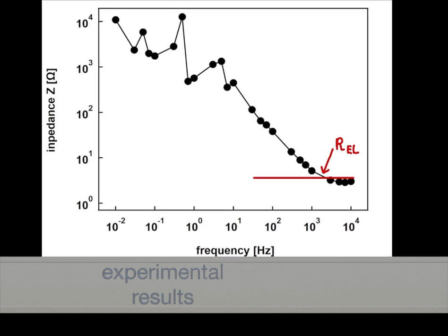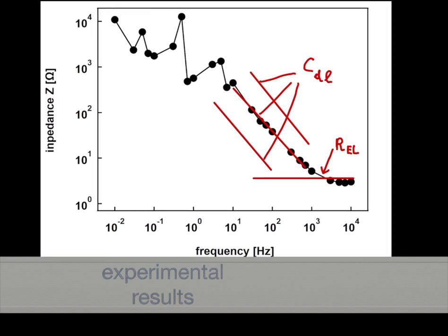You can easily evaluate the resistivity of the electrolyte between 1000 and 10,000 Hz. In the double logarithmic plot of impedance versus frequency, the location of the minus 1 slope is determined by the capacitance of the double layer. A shift to the left would point to higher capacitance, a shift to the right to lower capacitance. So we use CDL here as a fit parameter. The sum of the transfer resistance and electrolyte resistance is the fit parameter for the left part of the curve.